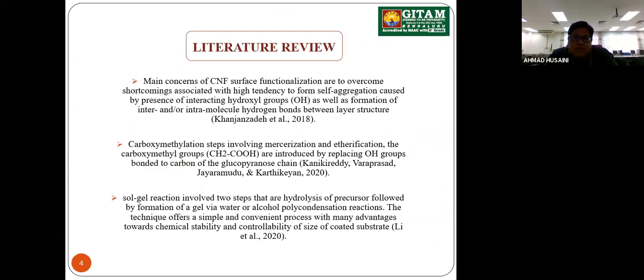Next. So for the literature review, the main concern of cellulose nanofibril surface functionalization was to overcome the shortcoming, which is the high tendency of self-aggregation caused by the presence of hydroxyl groups during formation of inter- and intramolecular hydrogen bonding. Carboxymethylation was the solution, a process involving mercerization and etherification, which replaces the hydroxyl group with the carboxymethyl group and causes a negative charge on the surface. The sol-gel reaction involves two steps, hydrolysis of the precursor followed by formation of a gel via water or alcohol during the polycondensation reaction. The technique offers the simplest and most convenient process with many advantages for adsorption activity. Next.